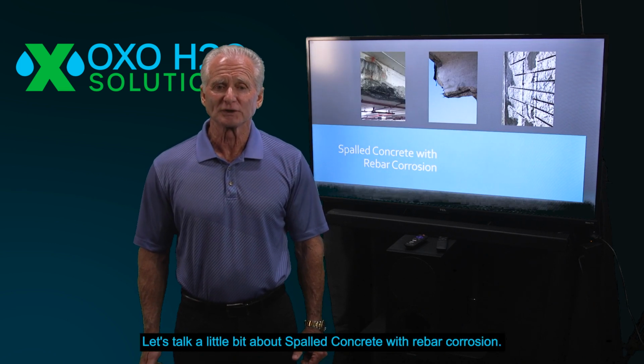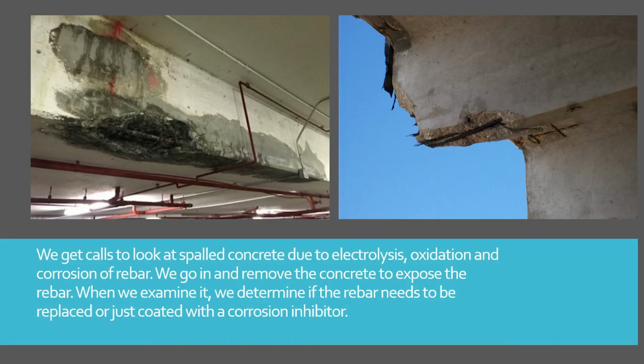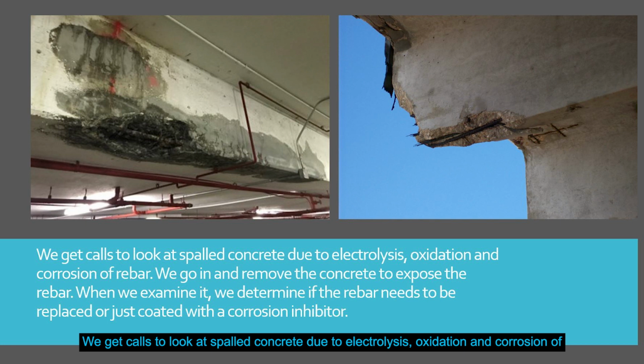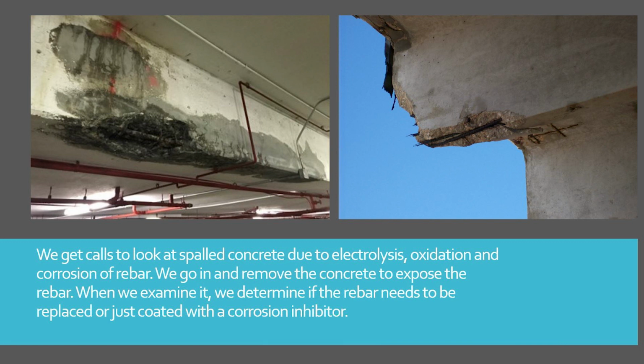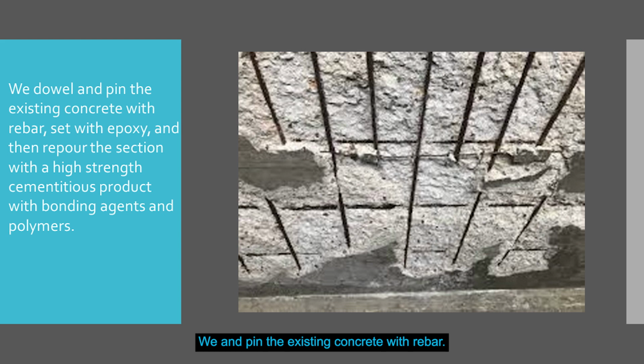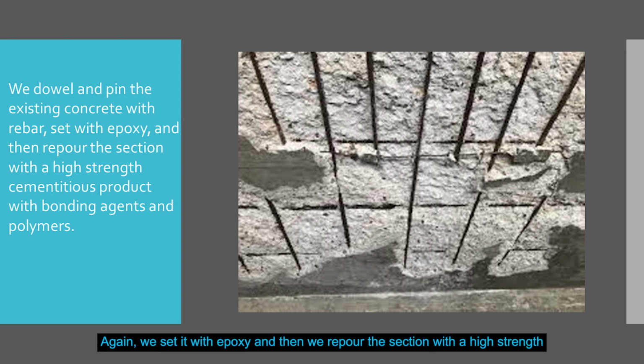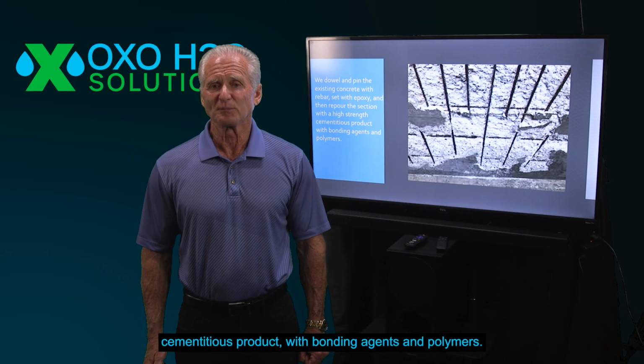Let's talk a little bit about spalled concrete with rebar corrosion. We get calls to look at spalled concrete due to electrolysis, oxidation, and corrosion of rebar. We go in and we remove the concrete to expose the rebar. We then examine it to determine if the rebar needs to be replaced or just coated with a corrosion inhibitor. We dowel and pin the existing concrete with rebar. Again, we set it with epoxy. And then we re-pour the section with a high-strength cementitious product with bonding agents and polymers.